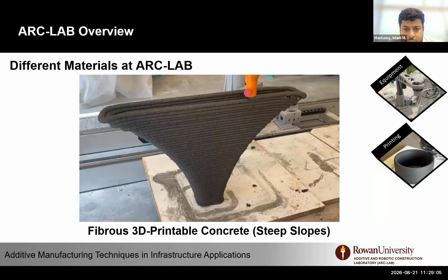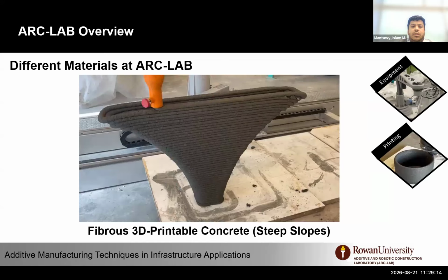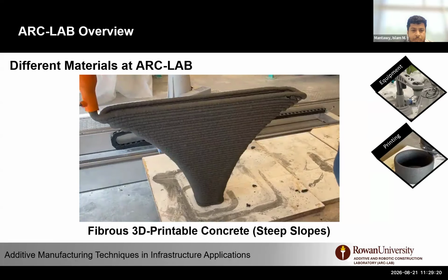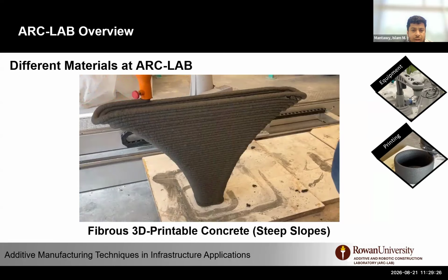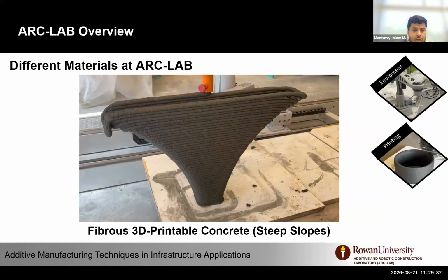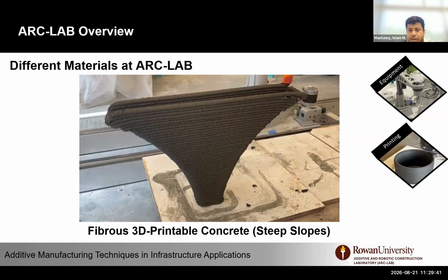We take that to what we call stress testing. So we print until failure and to the slope. As I mentioned, this is with no accelerant in the mix, and it was failing here by geometry rather than by the material. As you can see, partial collapses on the left side of this pier, and this was around a 65 degree slope from the vertical position. And we were able to identify that without fiber, we can achieve a 45 degree slope. With fiber, we can extend that to a 65 degree slope.